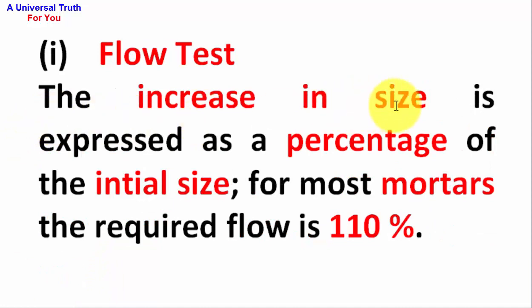The increase in size is expressed as a percentage of the initial size. For most mortars, the required flow is 110%.